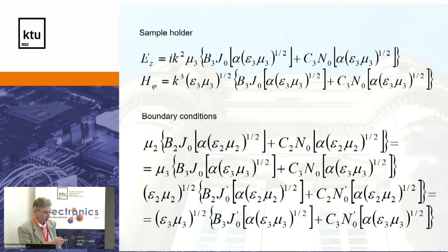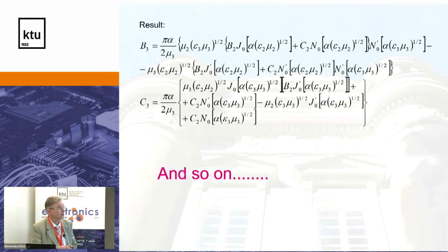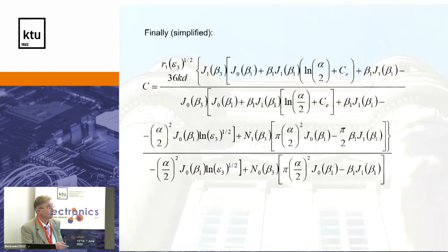So then you write for the sample holder, again, boundary conditions. And finally, you are getting the result for coefficients for the sample holder, and so on. I will skip the arithmetics. And finally, a simplified equation for the capacitance. Instead of the simple equation that C is equal to epsilon epsilon 0 times the area of a sample divided by the thickness, you are getting such a nice and easy expression.